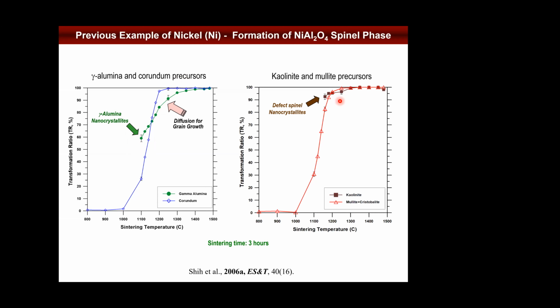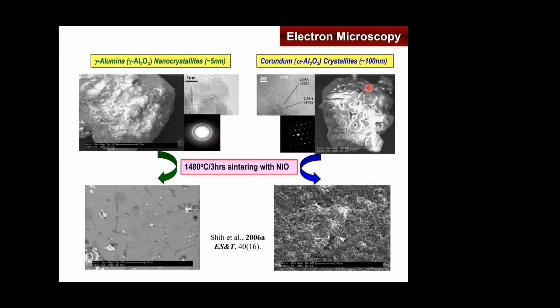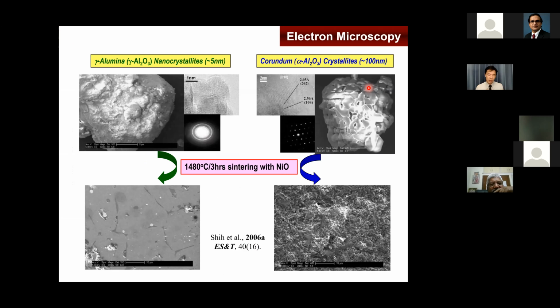Similar things we find out if you have the mullite, then you have the kaolinite, for example. Probably at lower temperature, you can use kaolinite as the effective ingredient to capture heavy metal like nickel. But when you go to relatively high temperature, both mullite and kaolinite, in fact, act the same to stabilize your nickel as the target heavy metal. So not only is the efficiency of the stabilization different, the product is also different.